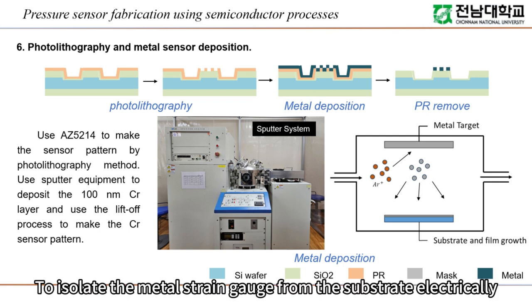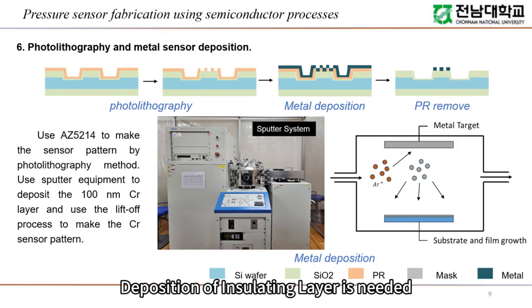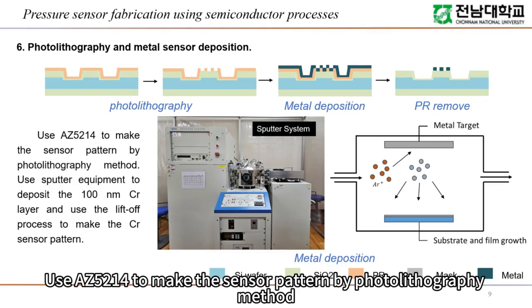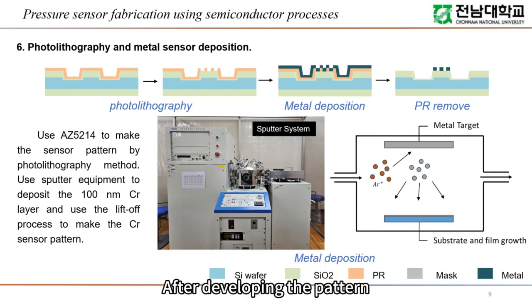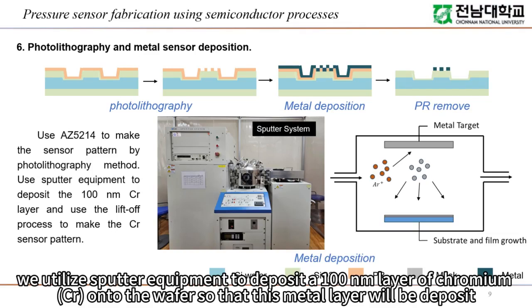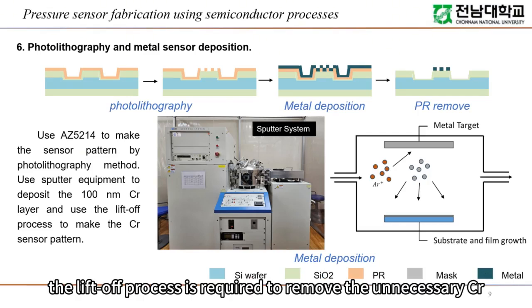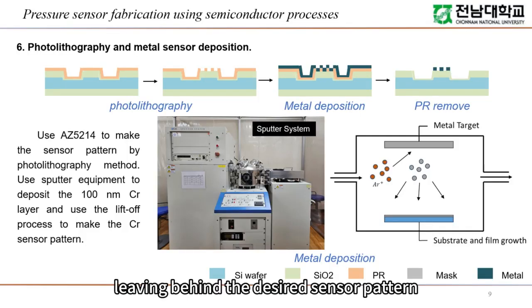To isolate the metal strain gauge from the substrate electrically, an insulating layer needs to be deposited. So you use AZ5214 to make a sensor pattern by the photolithography method. After developing the pattern, the sputter system will deposit a 100 nanometer layer of chrome onto the wafer. Then a lift-off process is required to remove the unnecessary chrome, leaving behind the desired sensor pattern.